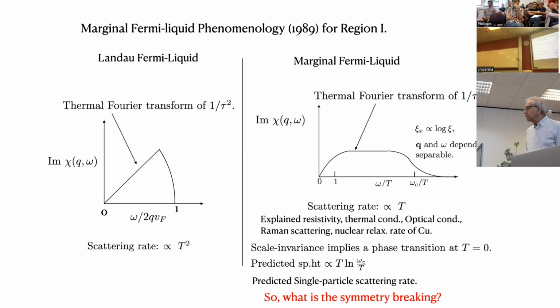It'll go as T squared in the single particle scattering rate, and if your material is such that there is some Umklapp scattering, then you will get a resistivity proportional to T squared with a different slope than the scattering rate. It's good to remember that in the pure limit, if there is no Umklapp scattering, the resistivity is zero at all temperatures. Okay? Not just the limit of zero temperature. Without Umklapp, you have to lose momentum for transport, for resistivity.